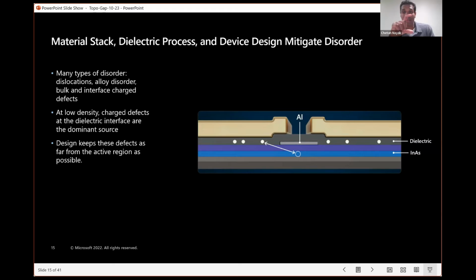However, we can't make it too thick, because if we make it too thick, then the induced superconductivity is too small. So there's a Goldilocks regime of a barrier layer that's thick enough but not too thick, and an aluminum strip that's wide enough but not too wide. So it's the width of the aluminum strip and the thickness of the barrier layer, two things we can control in the design.